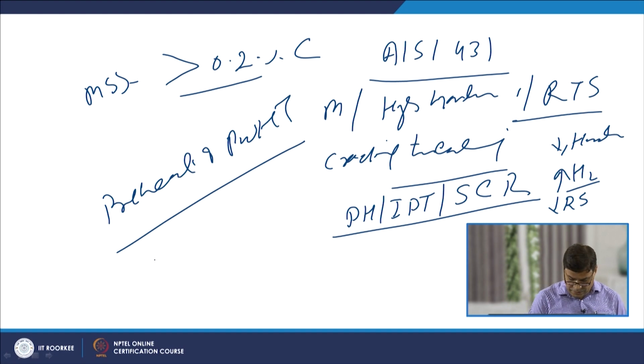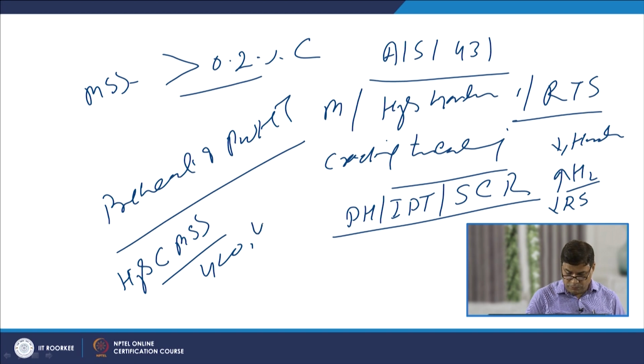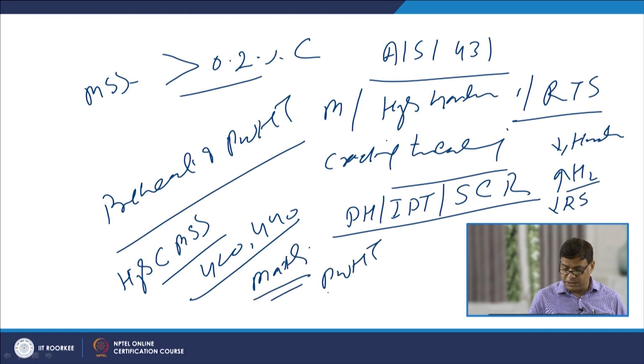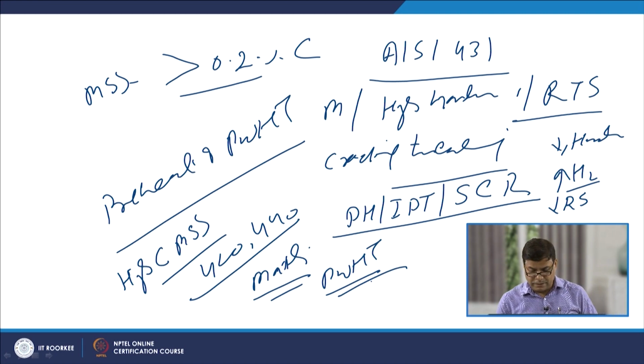cracking tendency. But further, in case of very high carbon martensitic stainless steels like 420 and 440, and when matching fillers are used, PWHT becomes mandatory to avoid the cracking tendency.